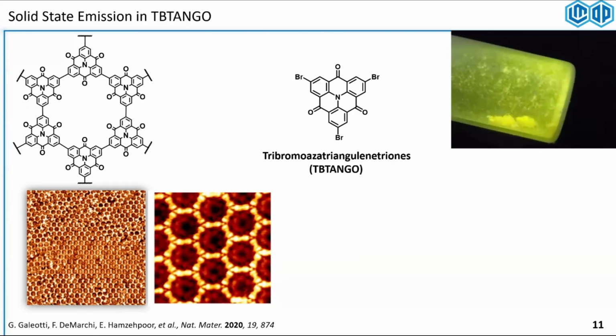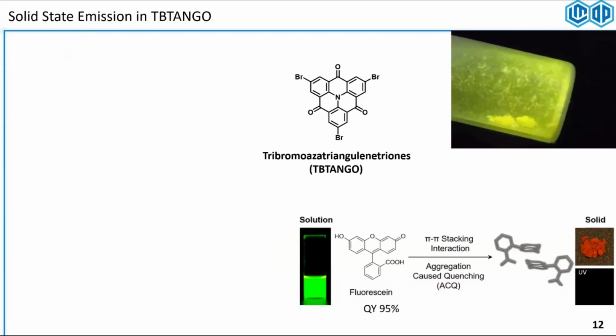I worked on this tribromoazatriangulenetrione molecule, short for TB Tango. And that was a whole different project that I wanted to do with it. With Federico Rosei at the time at INRS, we made monolayers of these 2D polymers. We studied their semiconducting behavior, their Dirac cone behavior, et cetera. But I found that the precursor itself in its crystalline state is highly luminescent, which for an undergrad who just started the PhD in 2017 was something bizarre for me, because I learned in my courses that organic molecules, especially flat molecules with carbonyls and stuff, in their solid state are normally non-emissive because of aggregation-caused quenching.